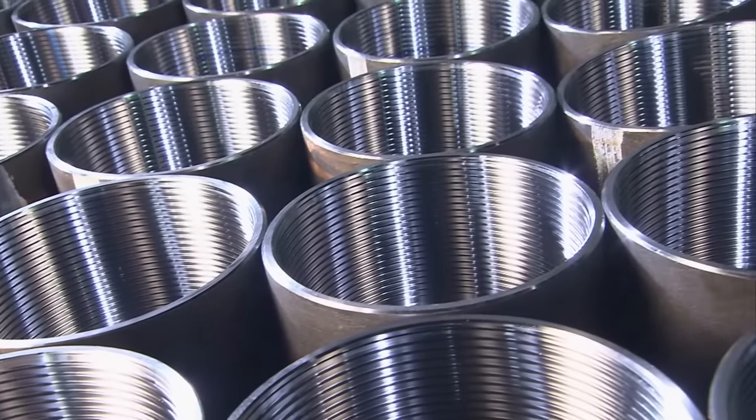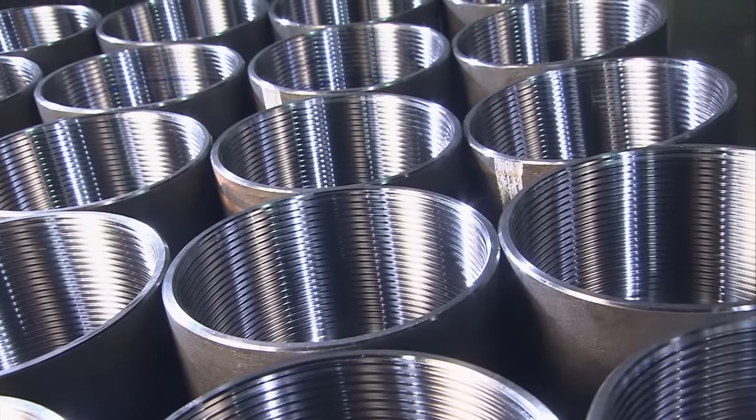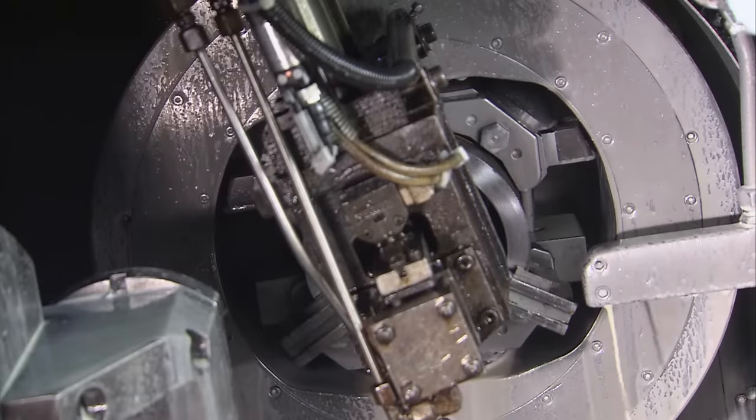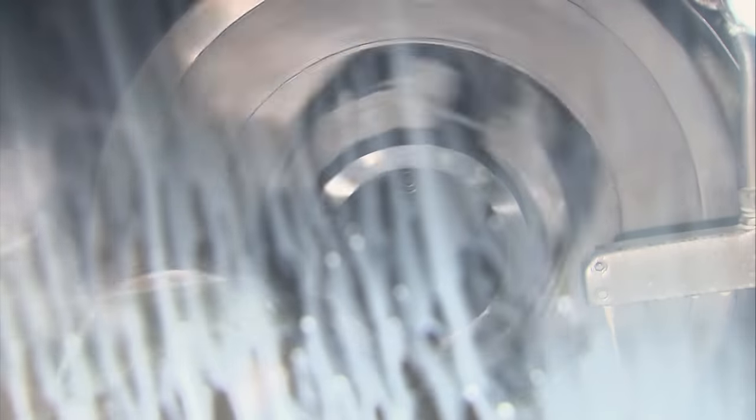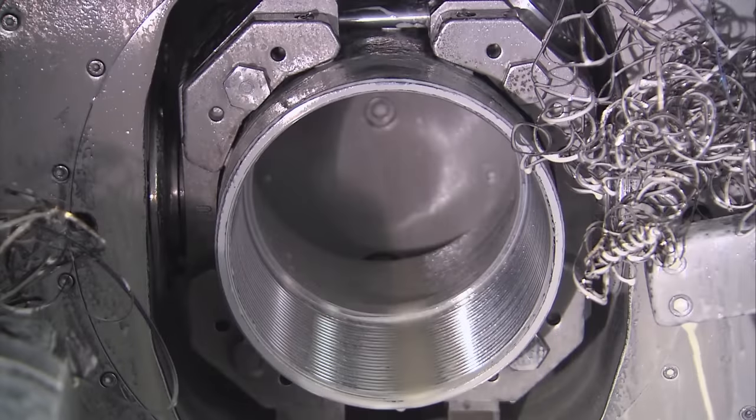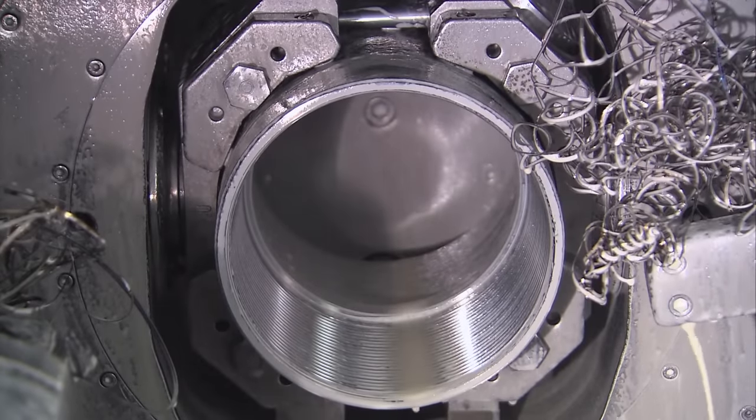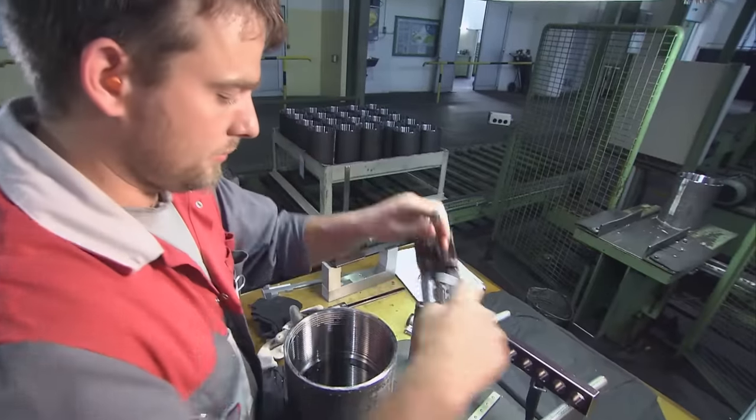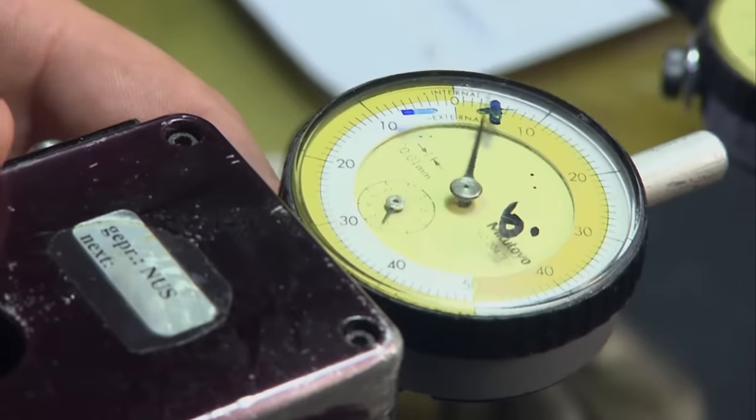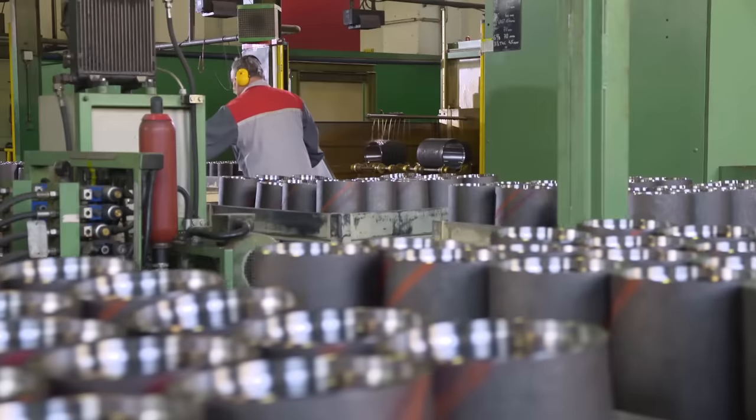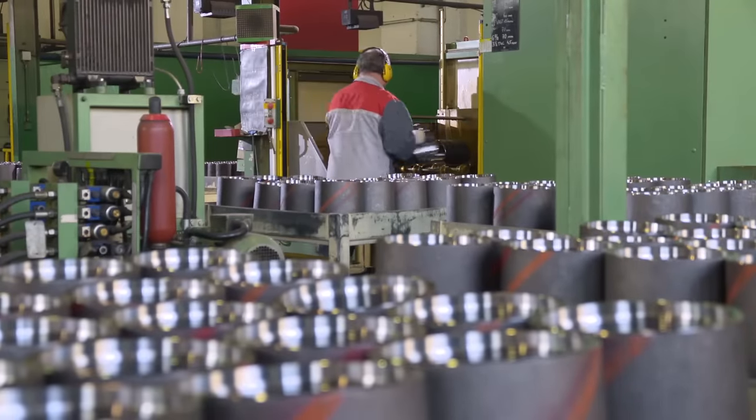The couplings required for producing finished OCTG are also made from seamless tubes. These tubes, referred to as coupling stock, are cut into blanks of specific length. CNC machines then cut threads in the blanks to make OCTG couplings. After dimensional inspection and non-destructive testing, the couplings are phosphated and moved to the thread lines, where they are installed on the threaded pipe.